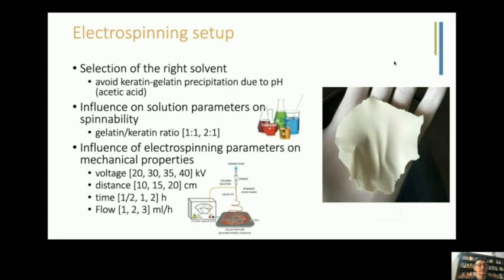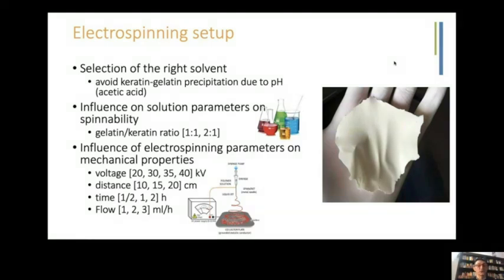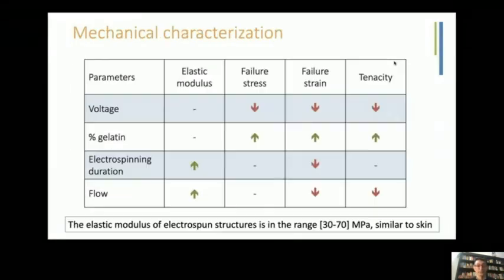Initially it's important to select the right solvent in order to have a well-defined structure, so that there is no trace of solvent in the final structure that can dissolve the single fibers. So we used acetic acid. We optimized the ratio between gelatin and keratin, which was 1:1 or 2:1, and we also tried to optimize the different parameters involved in the electrospinning process, such as voltage, applied distance between the needle and the collector, the time of extrusion, and the flow of the syringe pump.